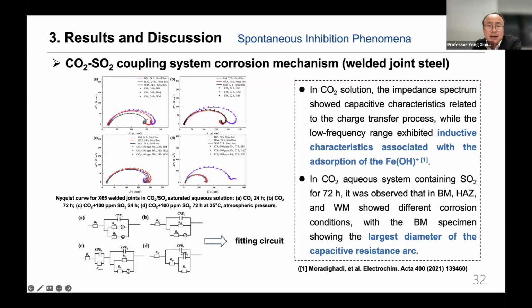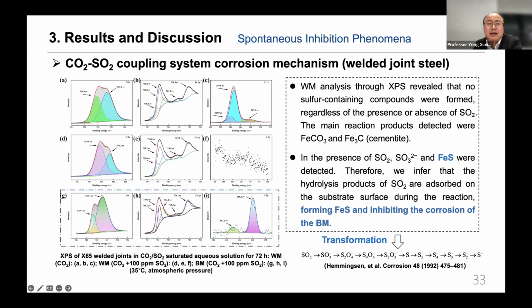We also did the EIS test and found the same things. You can see some absorption on the surface. And you can see for the base metal after 72 hours with SO2, there is a very big capacitive arc diameter. That shows the corrosion rate for the base metal is very low. And we also did some XPS tests. We found that some FeS, ferric sulfide, formed on the surface. Maybe this kind of thing reduced the corrosion rate of the base metal.